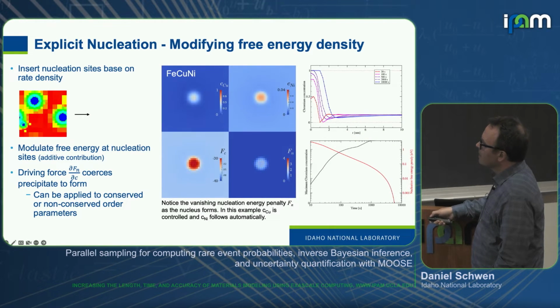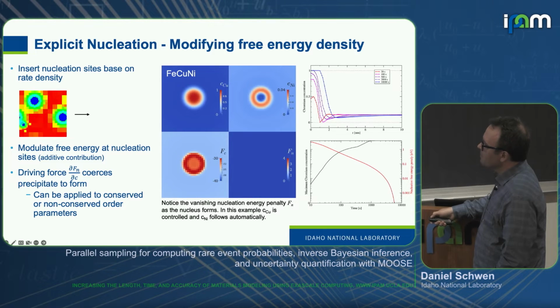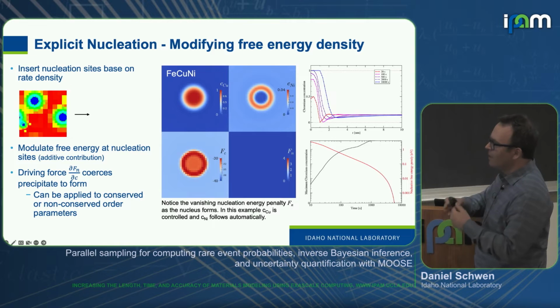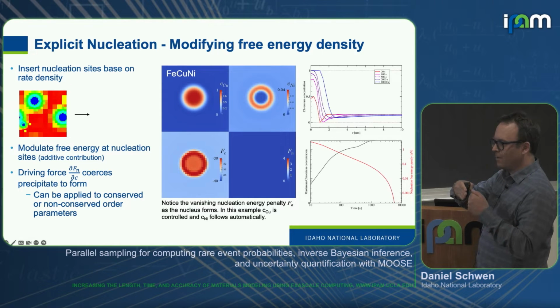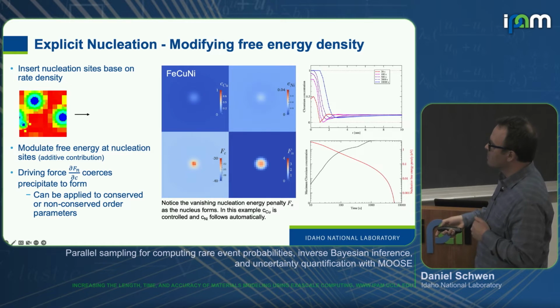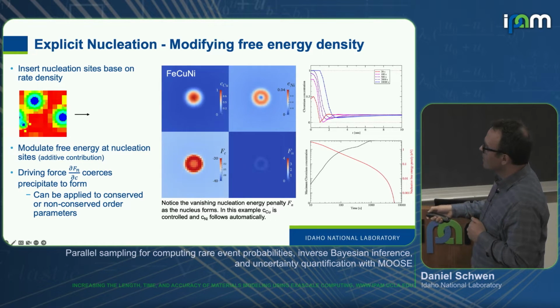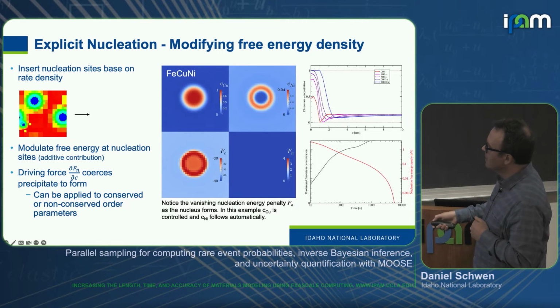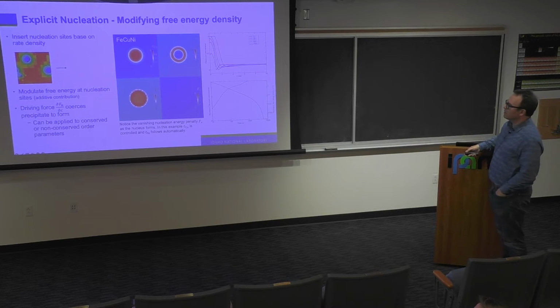Yeah, and the trick here is that we add this free energy penalty that penalizes concentrations that are not at my nucleating particle concentration. And that gives me a driving force to make the particle appear. And as it appears here, as a copper concentration, this penalty term just completely disappears. And at some point in time, we don't enforce it anymore at all. So this is a ternary alloy iron copper nickel that forms these neat core shell structures. Yeah, and the neat thing is this completely conserves mass. We're not explicitly moving mass around here.